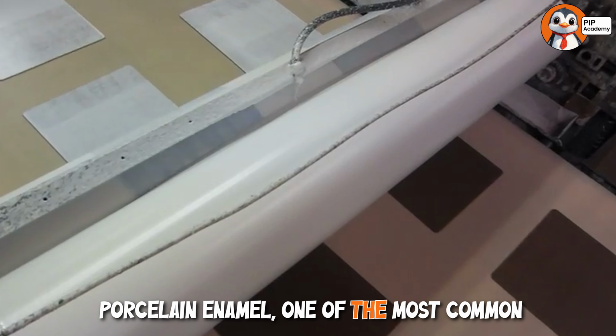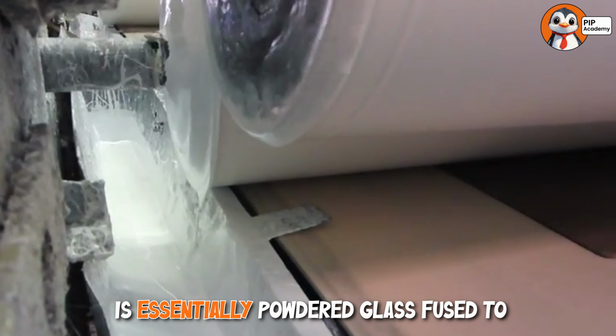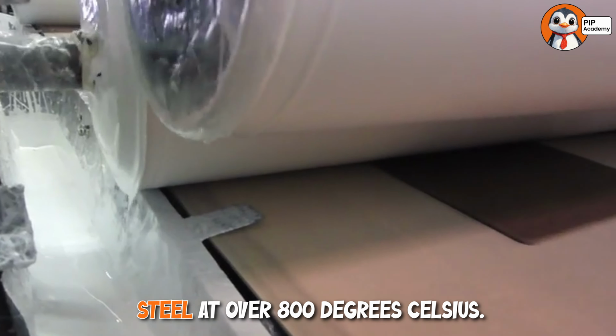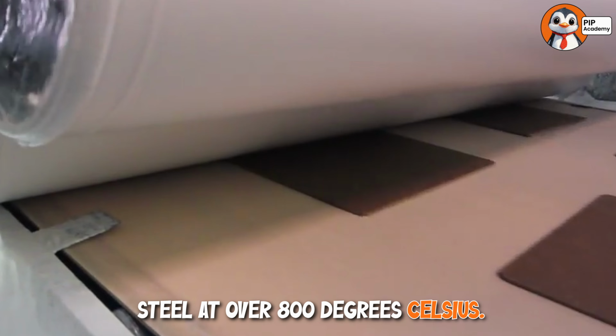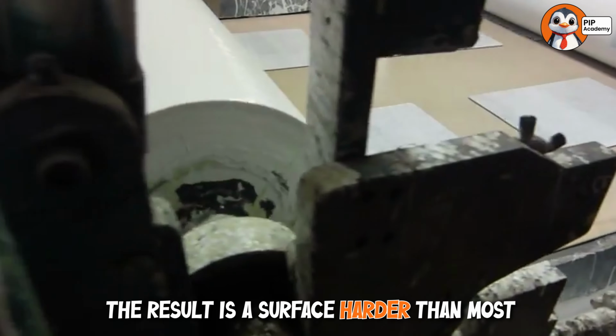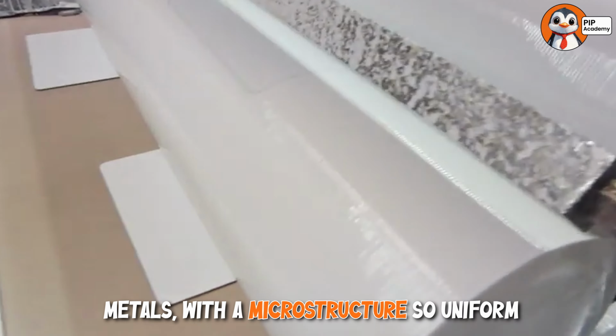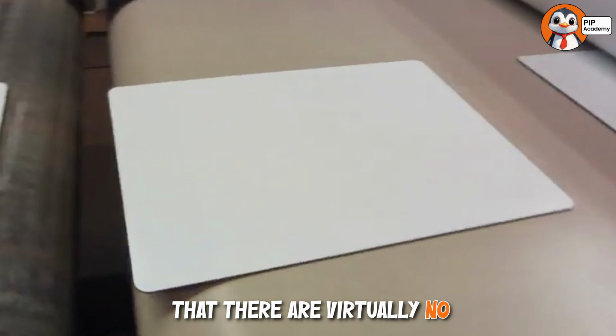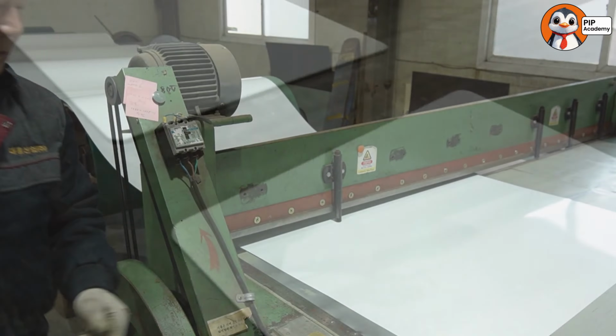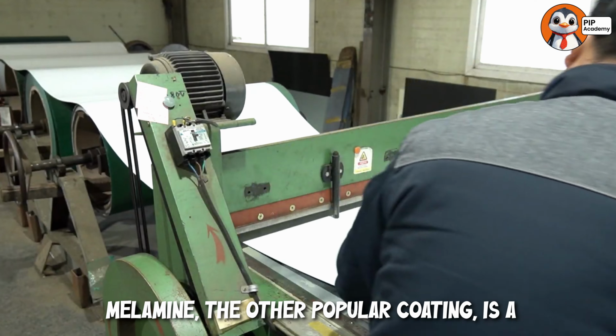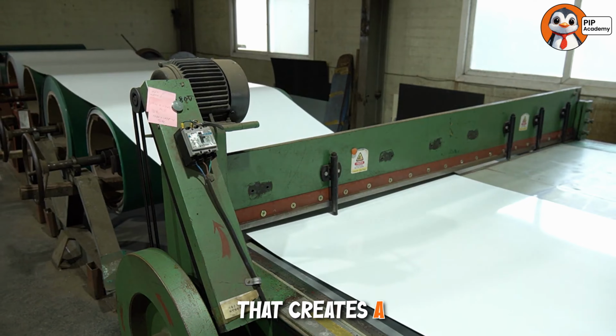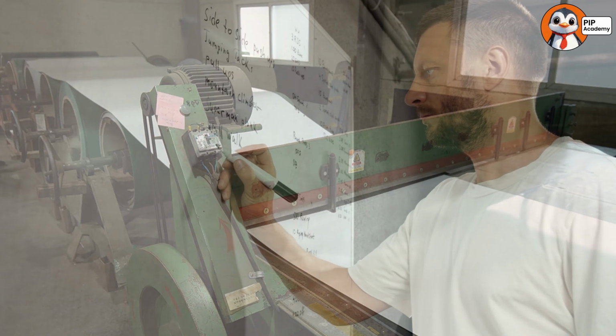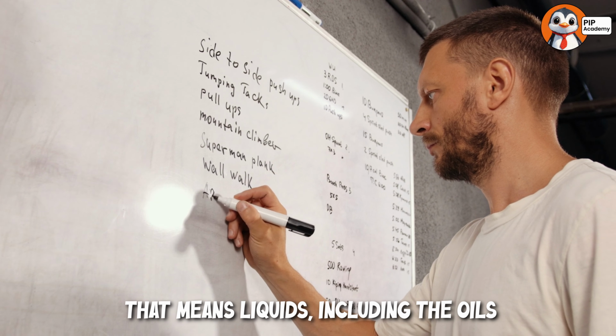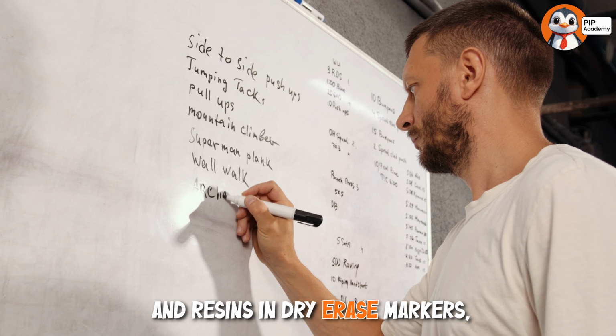Porcelain enamel, one of the most common whiteboard coatings, is essentially powdered glass fused to steel at over 800 degrees Celsius. The result is a surface harder than most metals, with a microstructure so uniform that there are virtually no pores for ink to seep into. Melamine, the other popular coating, is a thermosetting plastic that creates a similarly dense, smooth finish. Both materials have extremely low surface energy. That means liquids, including the oils and resins in dry erase markers, bead up instead of spreading out.